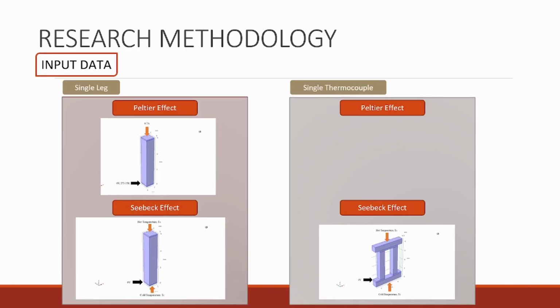So for the input data for single leg and single thermocouple, for the Peltier effect, we are going to introduce 0.7 ampere of current at the top of the leg, and the bottom will be grounded with 0 volts, and we will introduce a temperature of 273.15 Kelvin. And for the Seebeck effect, two different temperatures will be introduced on the top and the bottom of the leg, and it will still be grounded at the bottom. For the single thermocouple for the Seebeck effect, the same two different temperatures will be introduced.